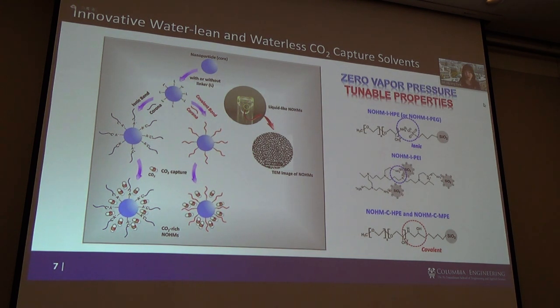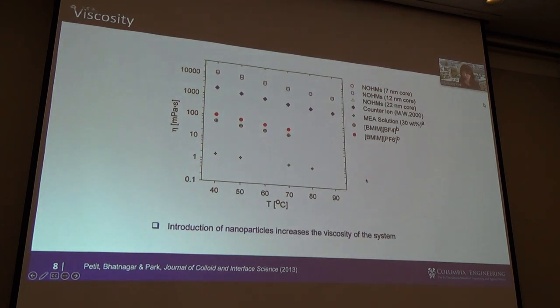And that's when we started to hypothesize that by tethering these polymers onto nanoparticles, as shown in this photo in the middle, it still behaves like a liquid-like material. There's a lot of tunability. But also, because we are stretching and creating this free volume between polymer chains, we thought that we are using both enthalpy and entropy effects to selectively absorb these small gas molecules like CO2 along the polymer chains. This was our hypothesis, and then we started testing this by looking at how to attach this CO2.